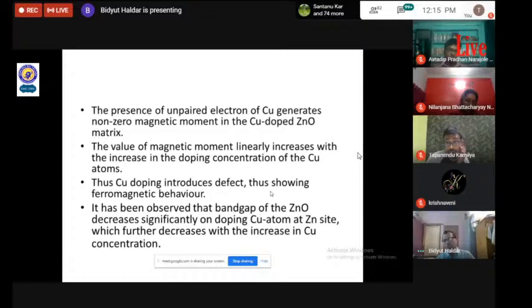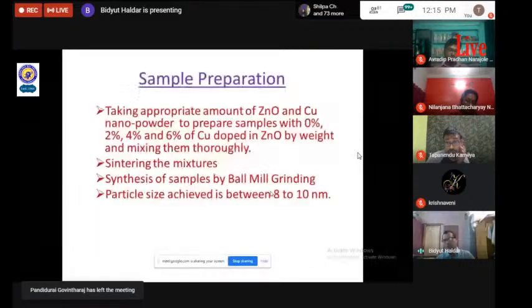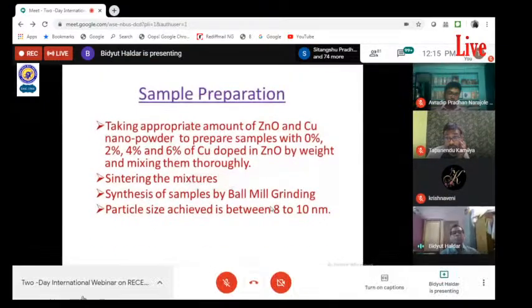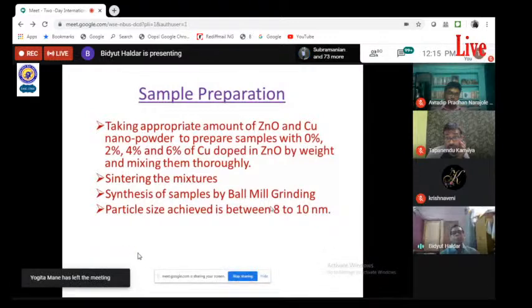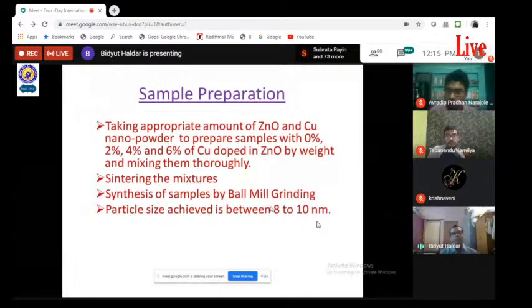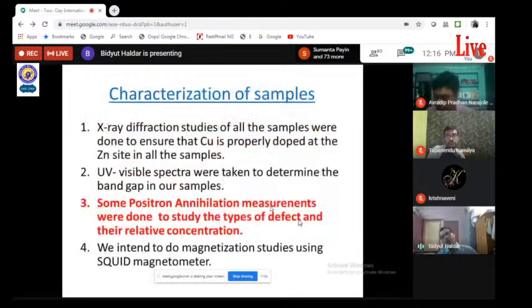So with this theoretical calculation behind us, we wanted to correlate with the experimental findings. Therefore, we made samples by taking appropriate amounts of zinc oxide and copper nanopowders to prepare samples of 0%, 2%, 4%, and 6% copper doped zinc oxide by weight, mixing them thoroughly, sintering them, and then using ball mill grinding, we achieved a particle size of about 8 to 10 nanometers. And then we are supposed to characterize the samples.